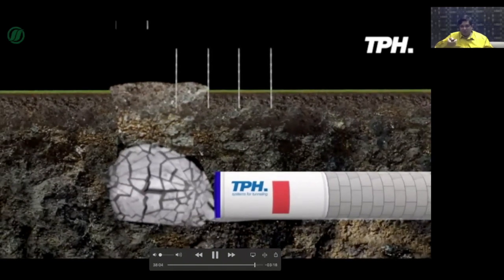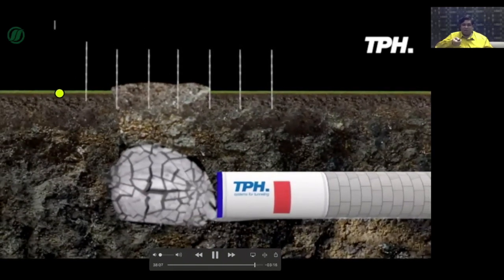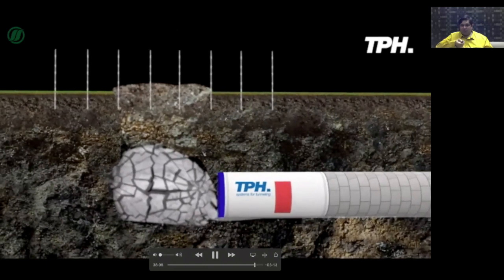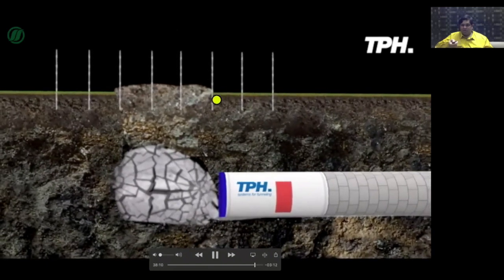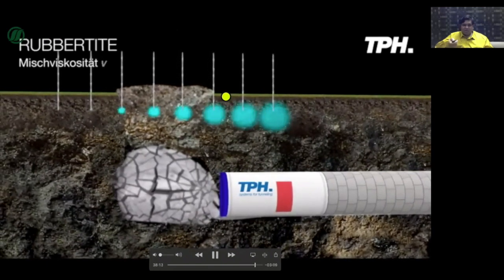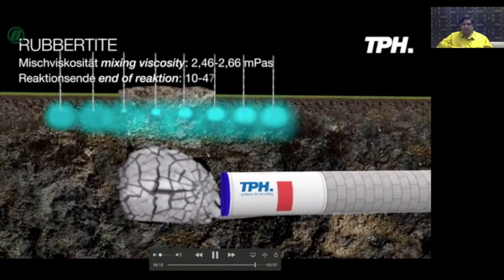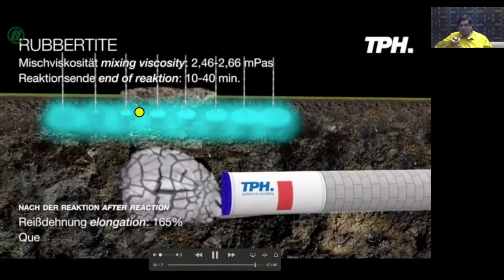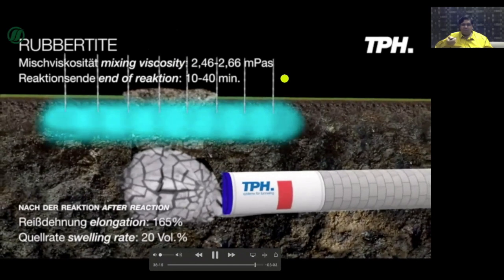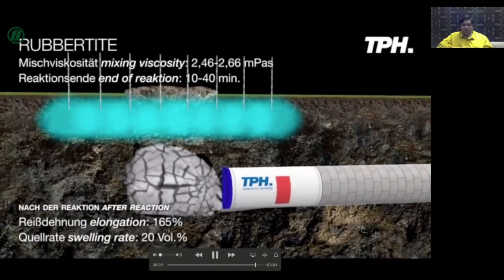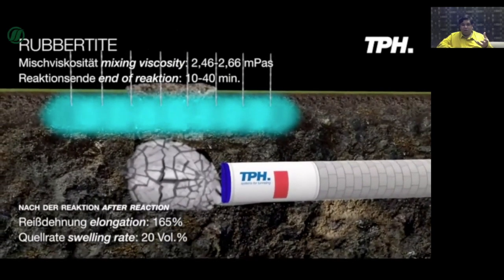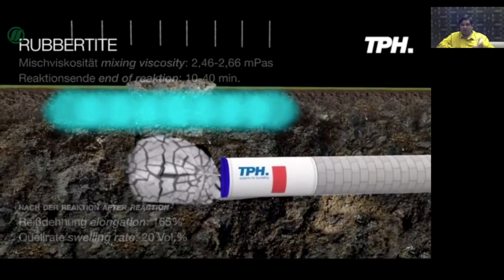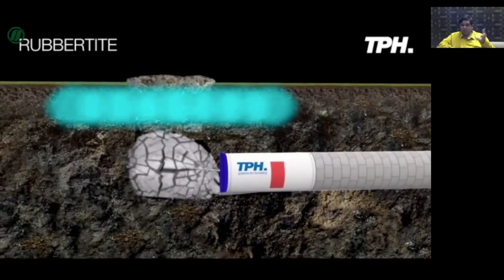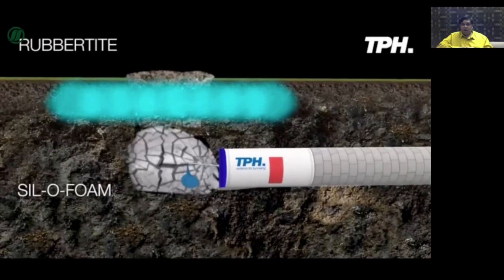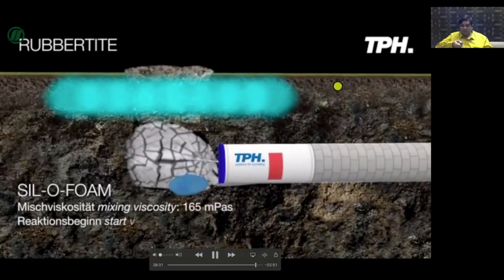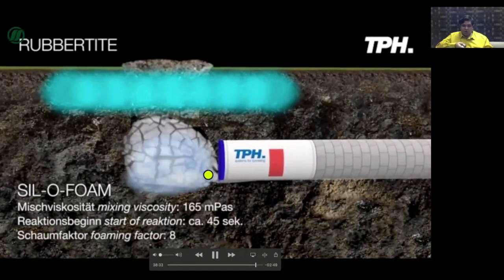Then you first do the stabilization with a methacrylate gel based system. So pretty much simple injection lances. Stabilize it with a material like Rubbertite, very, very low in viscosity, hardly 2.5, 2.6 mPas, and it's almost like water. So again, you can choose the reaction time. We can make it react in 10 to 40 minutes. No problem with groundwater.